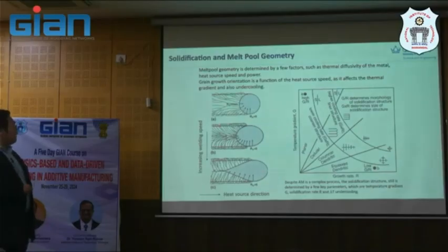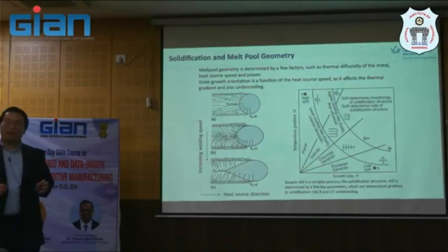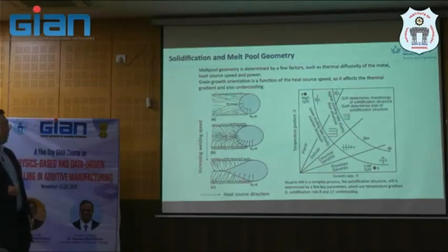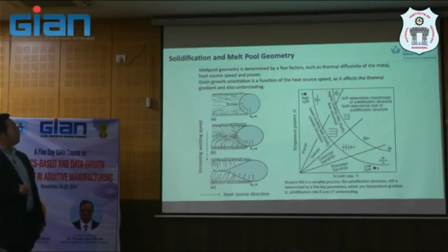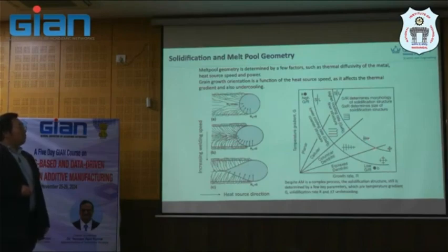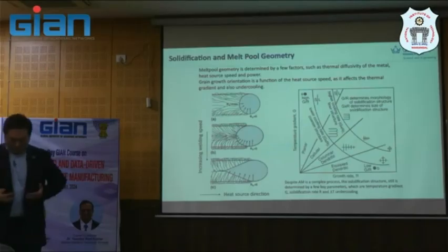As I told you before, increasing the scan speed, you get a kind of teardrop shape. I mean, the water drop shape here. And then this leads to different columnar grain microstructure. This is standard solidification theory, looking at the growth rate of the grains versus the thermal gradient here, and what zone your microstructure will fall into. But it seems that the growth rate and thermal gradient are very high. It should be in the zone of cellular and planar, not really the columnar and equiaxed that we want. But this one will fall into this after some time.